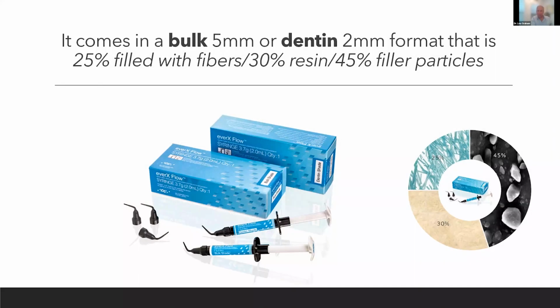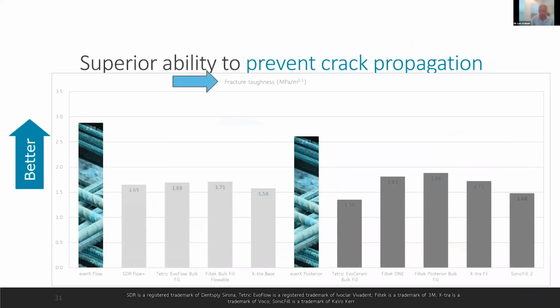As I said earlier, it's bulk or a dentin format. The bulk is obviously more translucent than the dentin color. The makeup is 30% resin, 45% filler particles, and 25% filled with fibers. And that's the unique part of this, the fibers. And when you look at Everex on what we call the fracture toughness scale, fracture toughness means we're trying to minimize crack propagation. And Everex Flow compared to all the flowables is almost, I'd say, 70% greater in fracture toughness, 70%. Okay, that is scientifically significant.